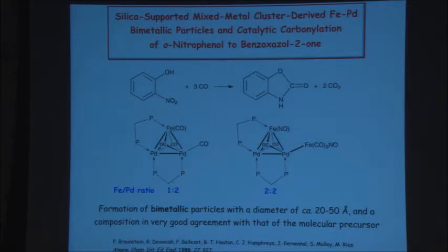So the particles here were all found to be in the 20 to 50 angstrom range, at least those we could see. At that time, of course, the sensitivity of the techniques was not as high as now. So if the particles were too small, they would just not be seen, which doesn't mean they were not present and maybe not active.